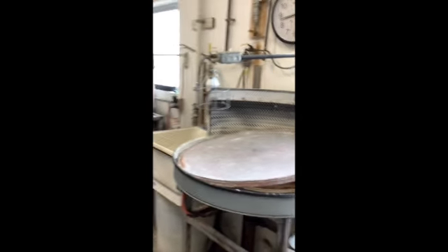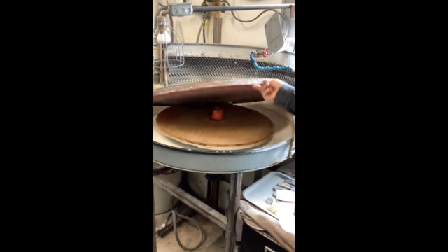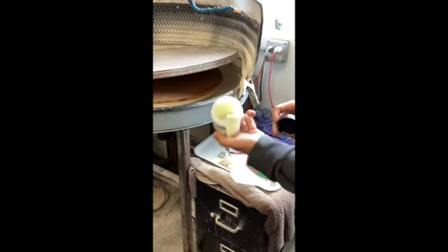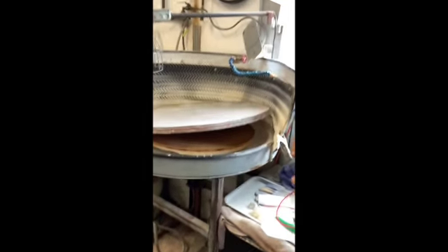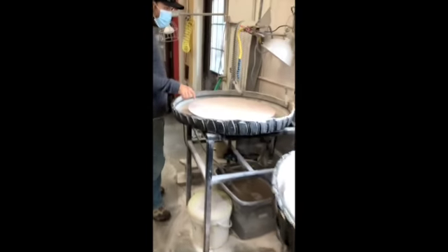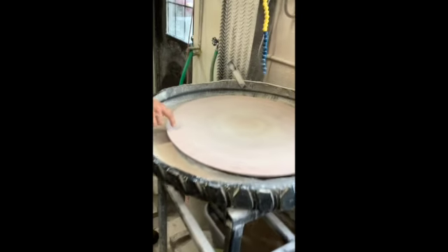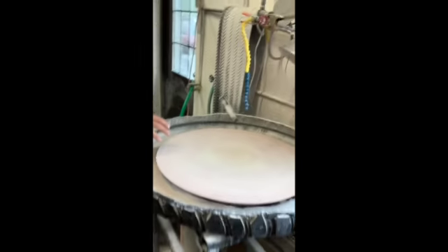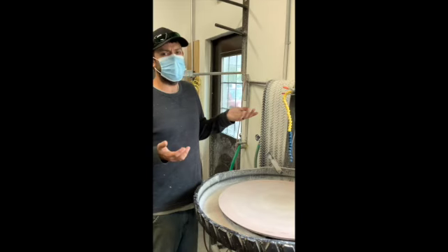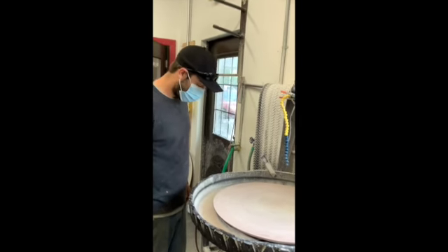Okay. And then as we go this way, these wheels, this one is made of wood, and it's got this diamond. It's almost like a powder sprinkled on top, essentially. It's just a finer and finer grit, like a sandpaper, from here to here. And then this one is felt, and we put a chemical on here called cerium, and that polishes the glass. It's like a polishing compound. And that's what makes it nice and shiny and pretty. Yes.